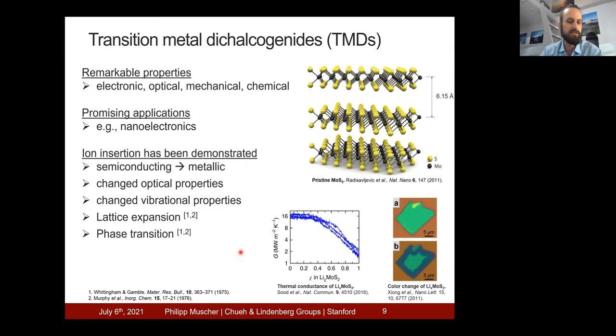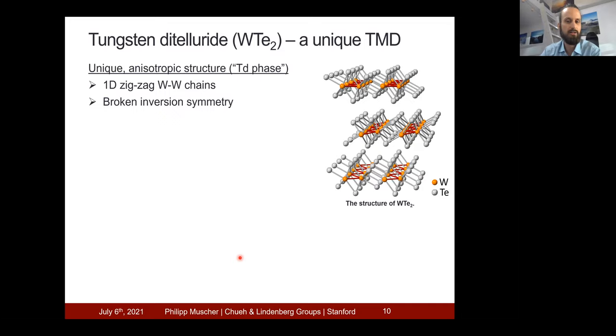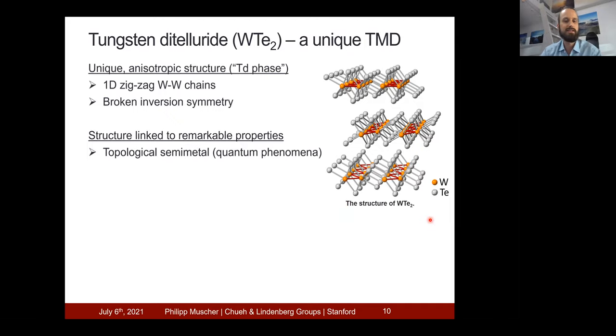And then in many of these materials, lattice expansions have been observed and phase transitions have been observed due to ion insertion. So in this talk, I'll be looking at tungsten ditelluride, which is a unique transition metal dichalcogenide. So the structure of this material is shown on the right-hand side, and it's a highly anisotropic structure because we have these one-dimensional zigzag tungsten chains. And this structure leads to a broken inversion symmetry, which in turn is linked to remarkable properties of the material. So this is a topological semi-metal, which makes it interesting for a range of potential quantum applications.